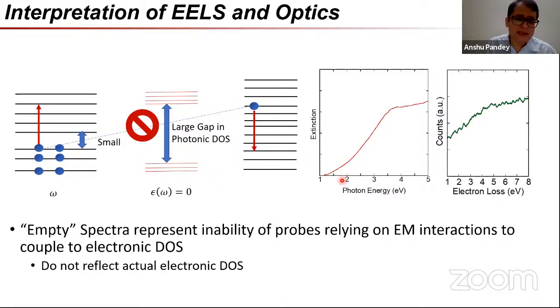What this does for us is that even if the electronic density of state is not sufficiently sparse, so we still have electronic states available, the fact is that radiation cannot really penetrate such a solid, for the simple reason that at particular frequencies we do have photonic states available, but at others we have very few states. So for most of the frequencies available, the system is actually impervious to electromagnetic radiation. And that would also have the effect of preventing normal interactions, such as EELS, which are not strictly occurring via electromagnetic radiation, but rather via an electromagnetic term at a certain frequency.